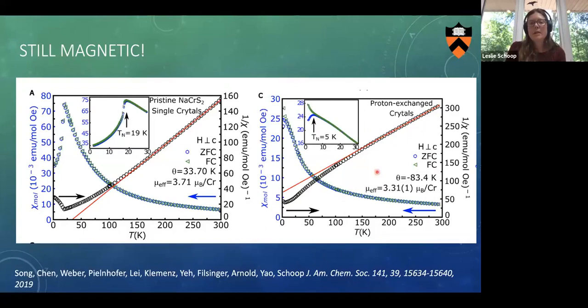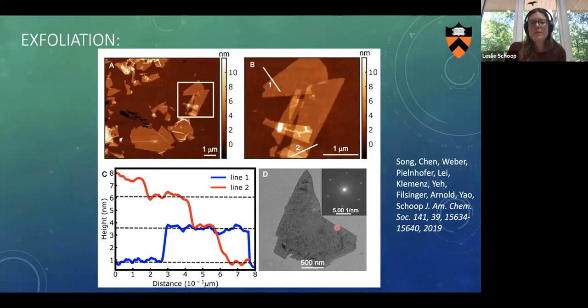But the million-dollar question was not the magnetism, it was: can we exfoliate this layered material? And the answer is yes, we can. So we just followed through with the original idea and put it in an organic base, and we can delaminate this material into monolayers, and the thickness agrees with the thickness we observed in the TEM of the crystalline layers. And so we confirmed that the layers we actually got are crystalline by putting it in the TEM and looking at these spots.